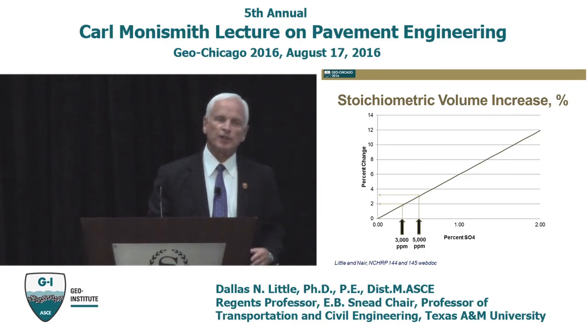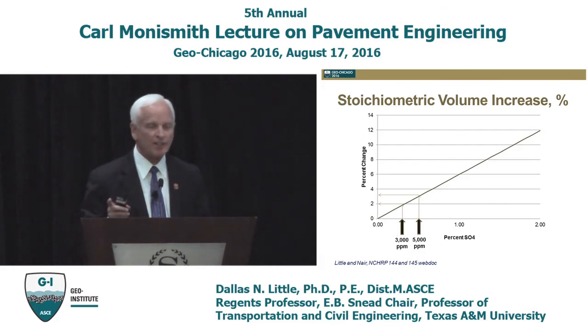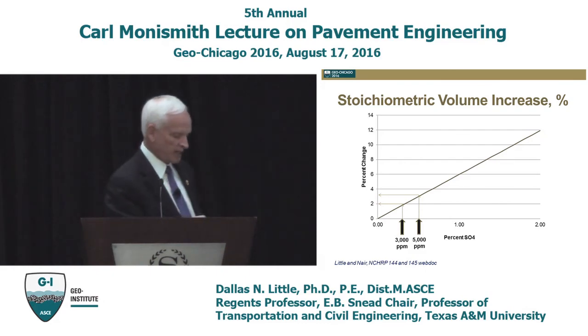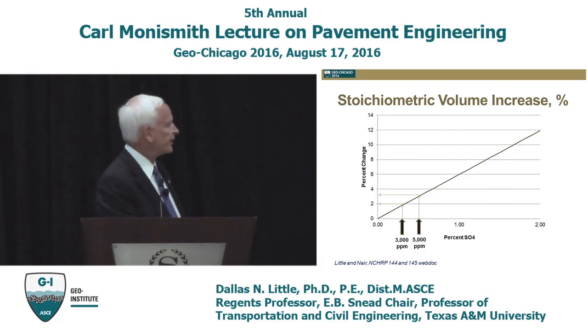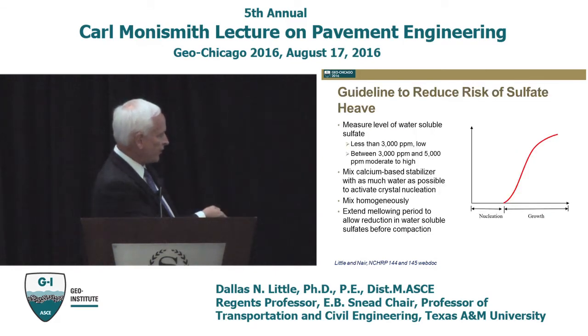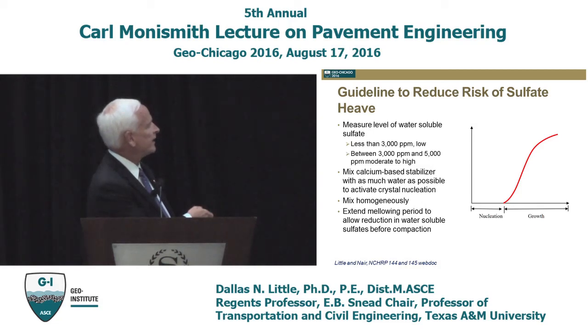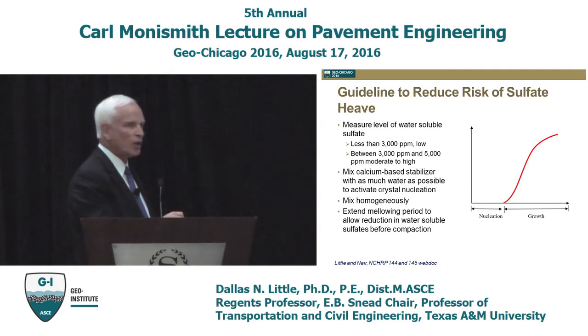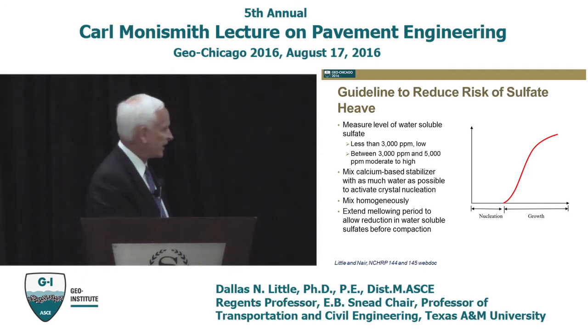Some of the things that we assumed in those days are not exactly right, but we fine-tune those. But our guidelines, which are in the report shown down here that I wrote with Sam Nair, NCHRP 144 and 145: less than 3,000 parts per million, your chances of having problems are low. Between 3 and 5, at least moderate. If you go up above that, you need to be very careful.